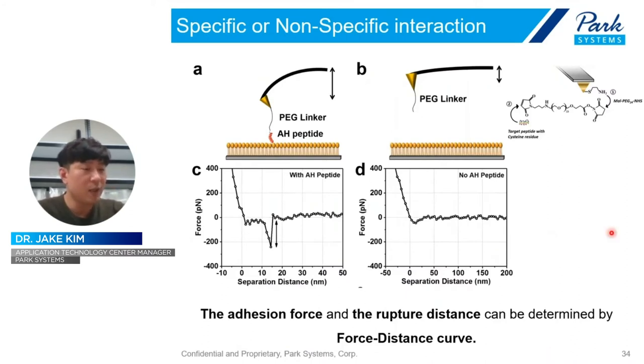Before finishing the session, I'd like to show you one very interesting application using FD curve. Generally, the adhesion from an FD curve means just the sample surface adhesion level. But if we can modify or add some material to the AFM tip, the adhesion means the interaction between this material and the substrate or sample surface. For example, in this case, this AH peptide highly interacts with this lipid monolayer substrate. So in the case of the AH-peptide modified AFM tip, we can see this adhesion force value. And this is the interaction between the peptide and this substrate.